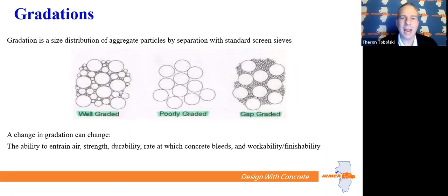And believe it or not, this kind of happens from maybe an accident in the production of an aggregate and a sample was taken and brought to a concrete plant, or maybe the way the concrete producer is stockpiling his aggregates, he caused one of these scenarios to happen. But this is exactly why we sample our aggregates on a daily basis, test them, and make sure they're of the right quality. Because if you have a gap graded or a poorly graded material, you can affect the way the air goes into the concrete, the strength, the durability, the rate at which the concrete bleeds, or the workability or finishability of that concrete.